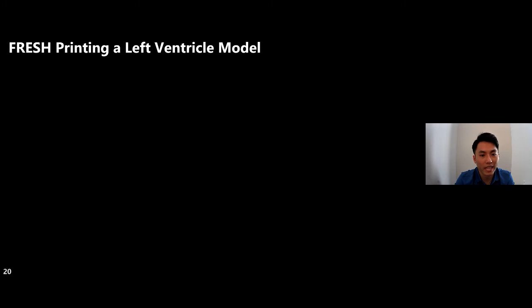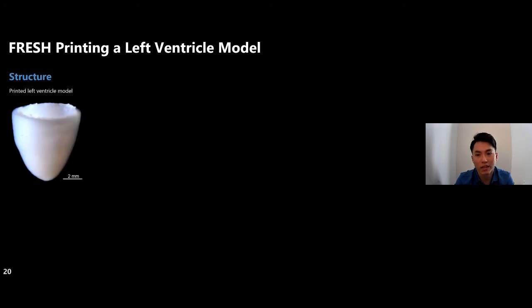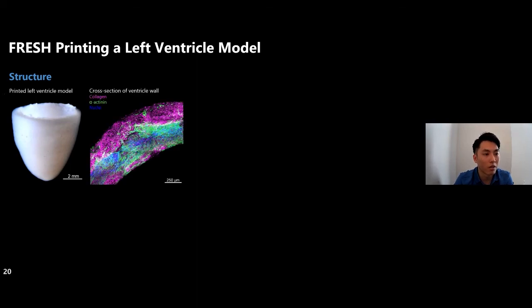Of course, a very key functional component of the heart is this contractile activity, right? That allows the heart to pump blood, which is orchestrated by the highly organized heart cells, cardiomyocytes. So here we created a simple model of the left ventricle, which is responsible for pumping oxygenated blood throughout your body. So we printed this left ventricle model out of collagen and stem cell derived cardiomyocytes. And you can see here through a cross section of the wall, we have distinct layers of printed collagen surrounding this central shell, or central layer, of cardiomyocytes.